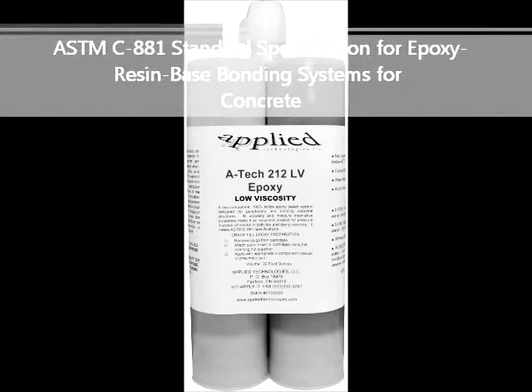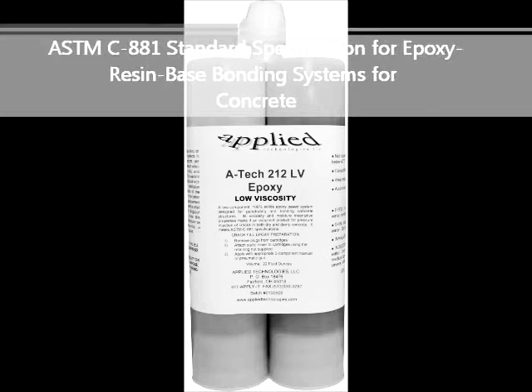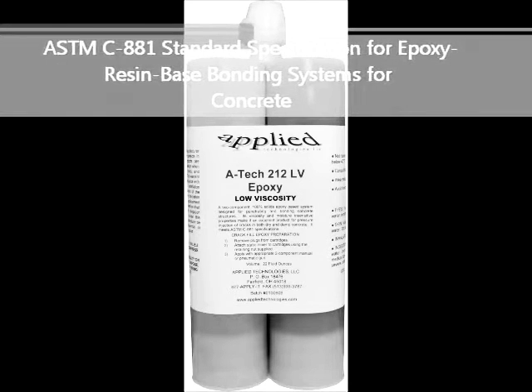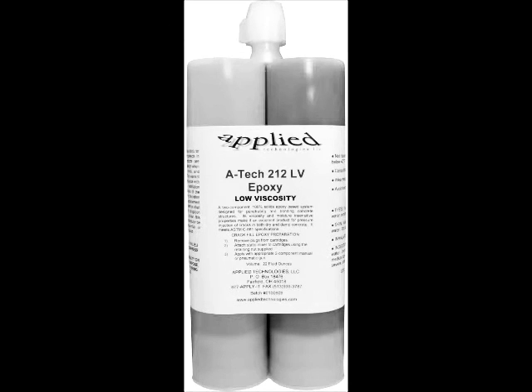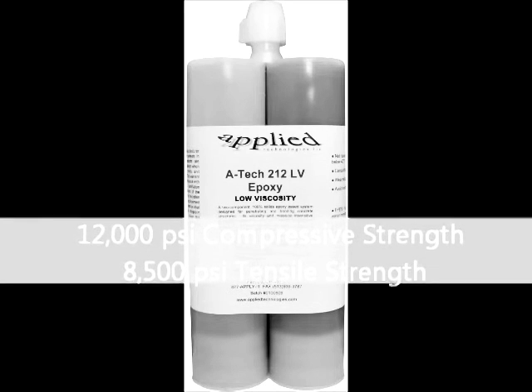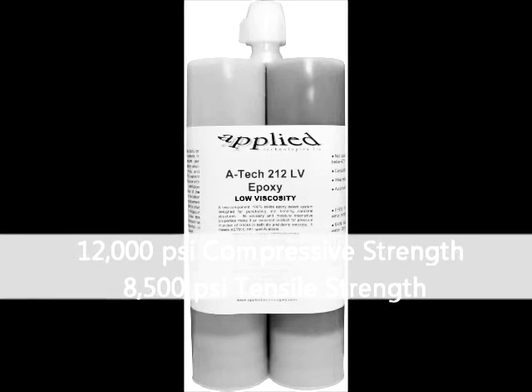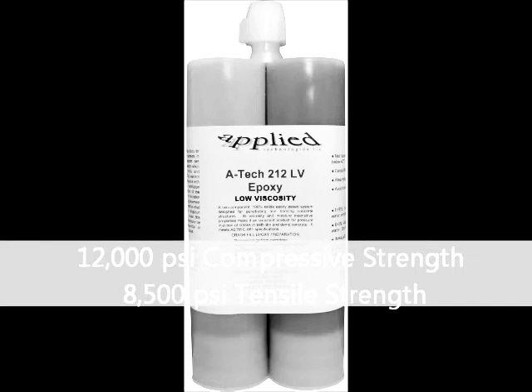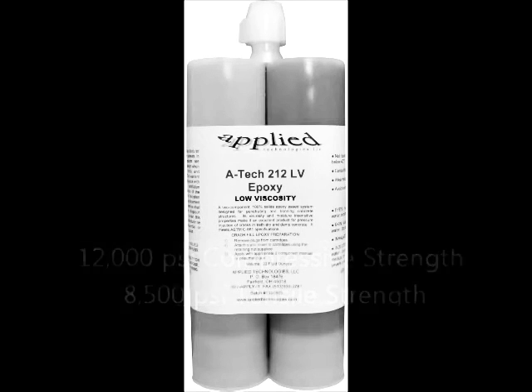A-Tech 212 meets ASTM C881, standard specification for epoxy resin-based bonding systems for concrete. A-Tech 212 has a compressive strength of 12,000 psi and a tensile strength of 8,500 psi. Both of these properties are higher than standard concrete.